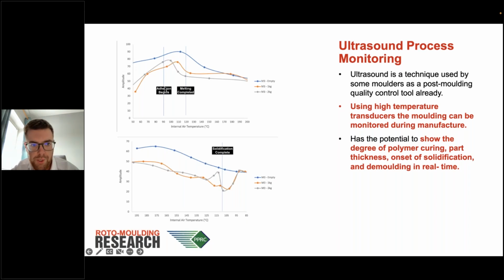And what this graph shows then is the onset of the adhesion, the point at which the melting is completed, and the effects of the thickness on the returning signal. And you can imagine this by if you were to ring a bell and then place a damp sponge onto it, the harder you push the sponge, or the more sound absorbing the sponge is, the more sound is going to be absorbed and the less ringing the bell is going to do. And that's what this graph is showing. So the 2 kilo molding absorbs more sound, and therefore the amplitude of that signal is reduced.